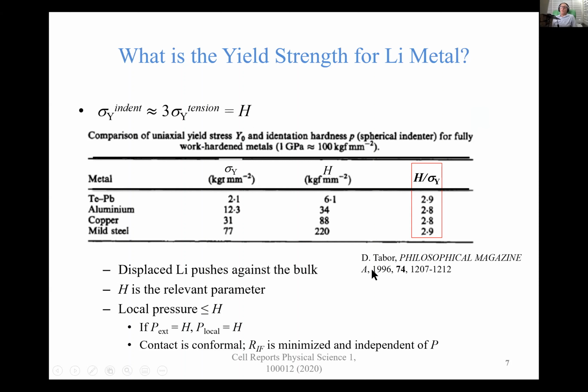So imagine that you're a lithium metal and a solid electrolyte is approaching you. That solid electrolyte has asperities or bumps on the surface, and those asperities are going to push into you and make you go plastic. So if you're lithium, the parameter that controls whether you go plastic is the hardness. The local pressure is always going to be less than the hardness, because if it tries to get to the hardness, the lithium is just going to flow. But if the external pressure ever actually reaches the hardness, then the lithium will flow.